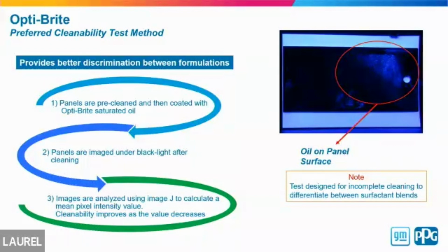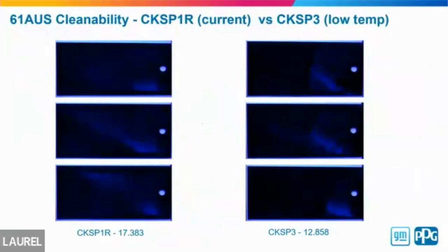Then we clean the panel, but we apply the process in order to partially clean it. Because if you clean it fully, you remove the oil, you remove the dye, and then everything looks clean, and you cannot differentiate between prototypes. So what we did, we partially cleaned, and then we screened the panel using ImageJ, the software that we utilize. And similar to a carbon mapping, we looked at pixels of those dyes. It gives you pretty much the coverage of the remnants of the oil on the panels. And then we compared between prototypes, or between our control, which is our current cleaner.